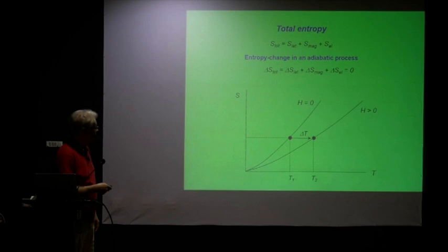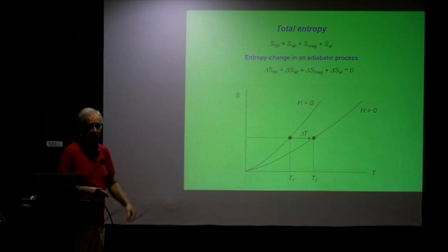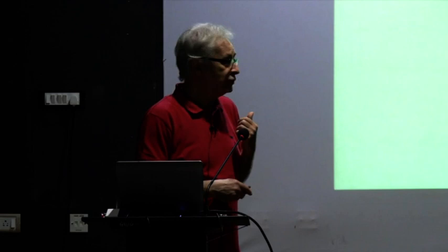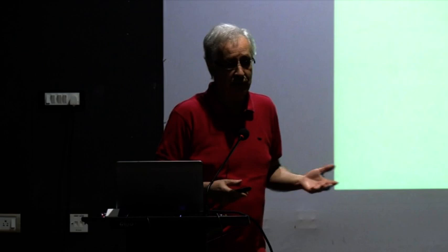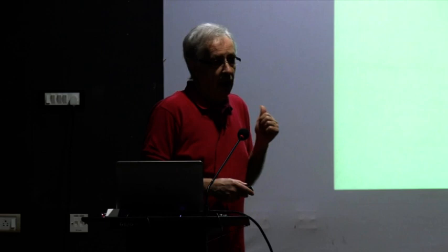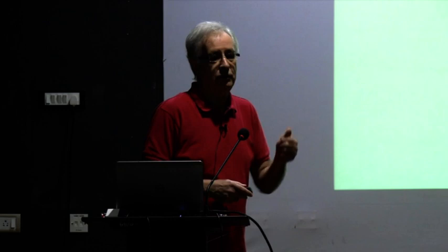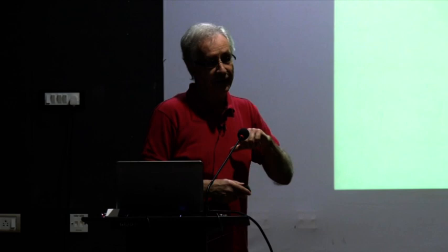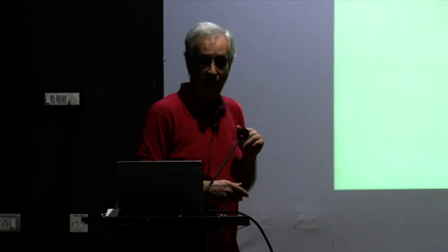The total entropy of a system is given by the lattice, magnetic and electronic contributions. At least we think that they are separable. It's a thermodynamic relationship. It's the additivity of energies in particular, in principle. This is valid, perhaps, only in the case when you are sitting in a single thermodynamic state, when the whole process is occurring within a single thermodynamic state. Now, when we have structural transitions, when we have field-induced transitions and things like that, this starts becoming problematic. Okay, we'll get back to that anyhow.